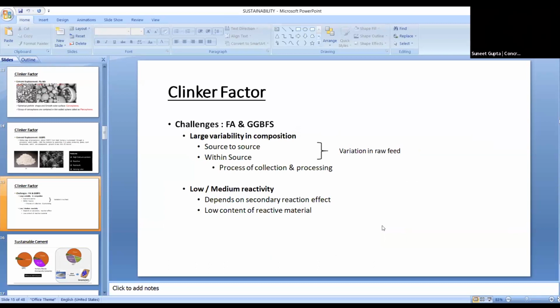But the challenge with fly ash and GGBS is that the variability is from source to source, or even within the source, because of the way we process and collect the fly ash or the slag, there is a large variation. And the variability is because of the variation in the raw material which is being used in making this fly ash or the slag.